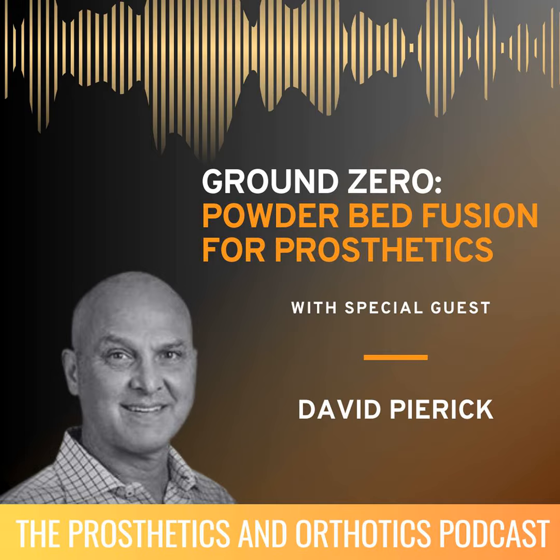And then we also, like orientation, for example, and there's a bunch of other factors that have a really big effect on that. Did you look a lot at orienting parts and other kind of things like that? We looked specifically in orthotics, we looked at print orientation relative to fatigue life and strength. And we found some things there that, if I recall correctly, it was better to orient in the vertical direction that gave you a little bit more, the horizontal direction, which gave you a little bit more fatigue life. So there are tips and tricks that we have.